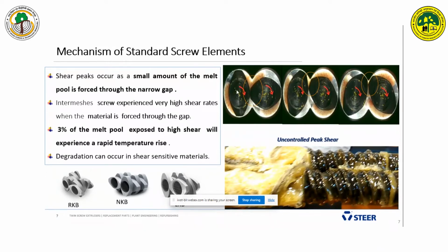If you see the first picture, the screw starts rotating. If you have fully melted material in the first screw, when the screw starts rotating, between the screw gap, which we call a narrow gap, a small amount of melt is trapped in the last screw. The screw starts rotating slowly and hardly 2 to 3% of molten melt is trapped there. And every rotation, because of the peak shear, it degrades the polymer and also increases the melt temperature, which leads to the degradation of the polymer. The dip, if you see, is called peak shear.